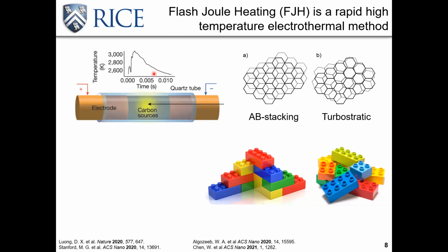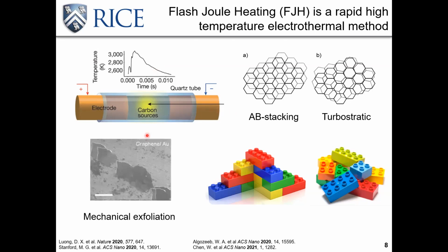Then we did a simple test. We sandwiched the sample powder between two silicon wafers, and then we used a monodirectional mechanical force to exfoliate it. As you can see on the wafer, we can see the few-layer material with the same edge shape as shown here. And this result indicates that the mechanical exfoliation can be used to coat the silicon wafer.